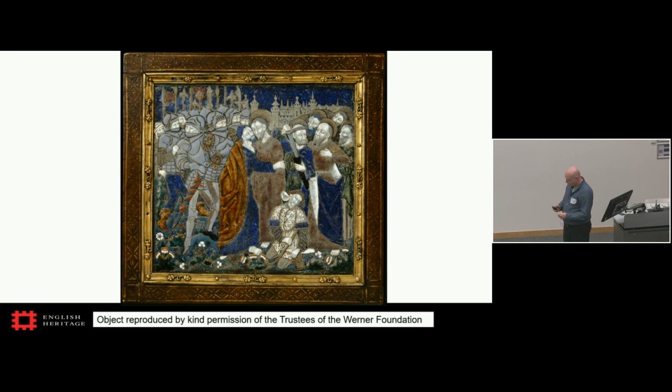And for those of you that know about glass degradation, the blue panel here and the purple panel here show obvious signs of chemical degradation. They're not as translucent as the surrounding glass. They're now matte as opposed to gloss. This is a reaction of the water vapour, and it can be other chemicals in the air, with the glass, and it's pulling the sodium and potassium out of the glass onto the surface and leaving a thin altered layer, sometimes called a gel layer, on the glass surface.